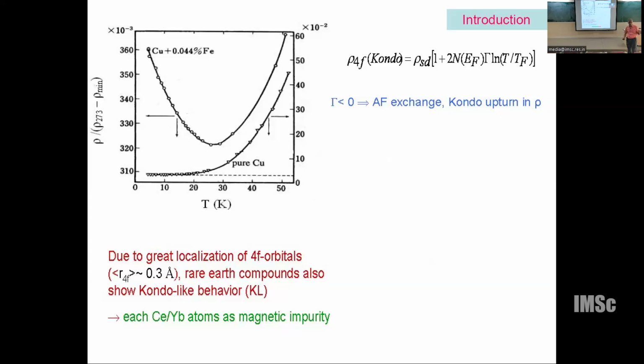And then Kondo from Japan came, and he used second order perturbation theory to explain. At high temperature, the local magnetic electrons are free. At low temperature, they get bound by the conduction electrons in metals. They get antiferromagnetic coupling. They become essentially non-magnetic. It's called the Kondo singlet, in honor of Kondo. They form a singlet ground state. Therefore, you lose magnetism. And the theory says the resistivity goes up logarithmically with decreasing temperature. There is a minimum in the temperature dependence of resistivity, which is the signature of the formation of the singlet ground state of the local moment.